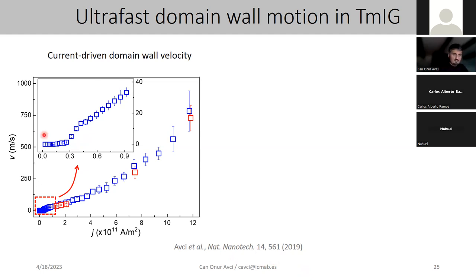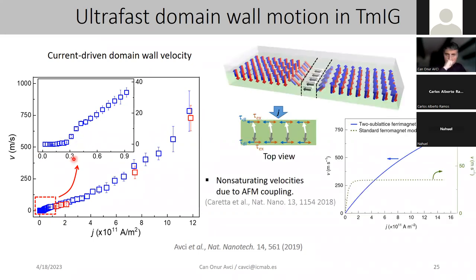in 2019. Right now we know that domain wall velocities could reach several kilometers per second for certain other systems, but at that time this almost 1 kilometer per second was one of the largest values found. And also this transition between creep and flow regime is one of the lowest values. And the reason for these very fast velocities is basically the ferrimagnetic behavior of the film.